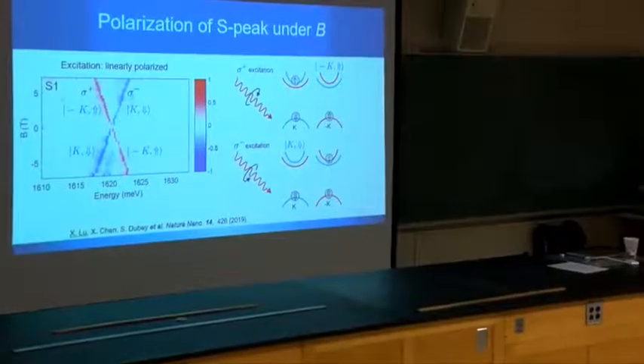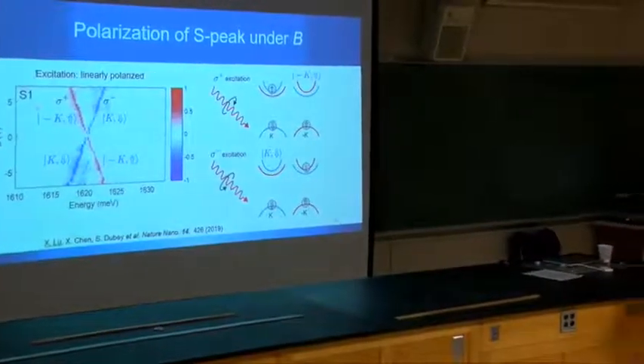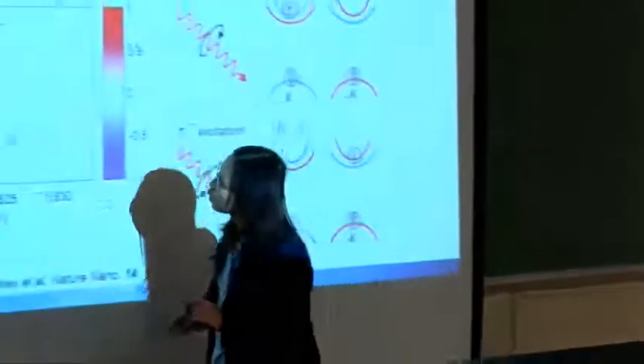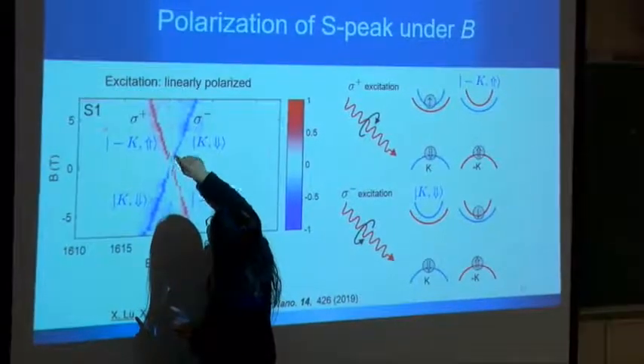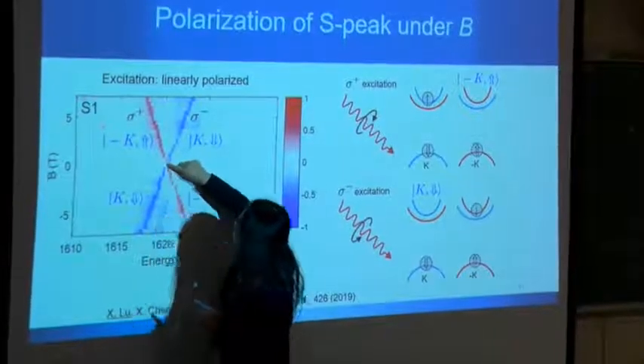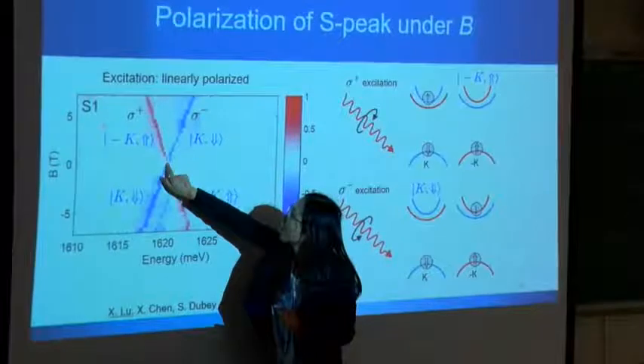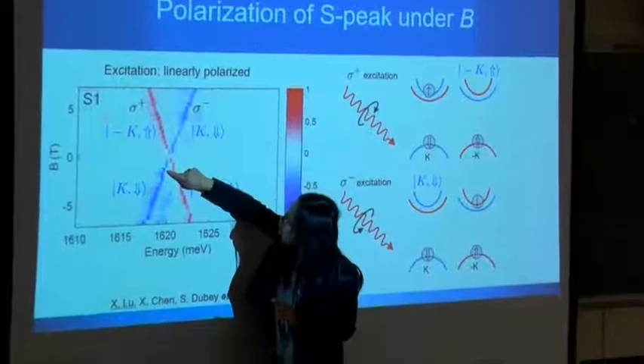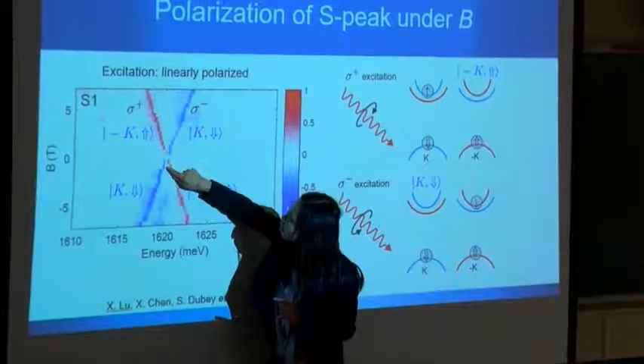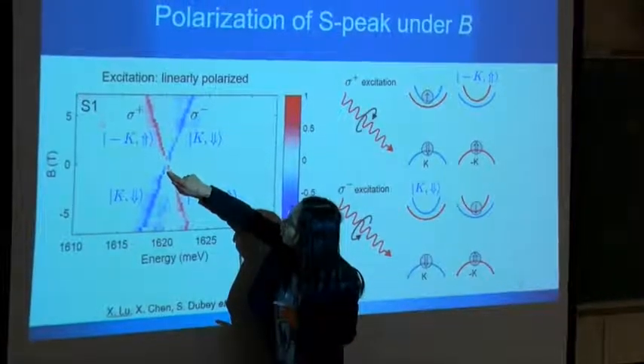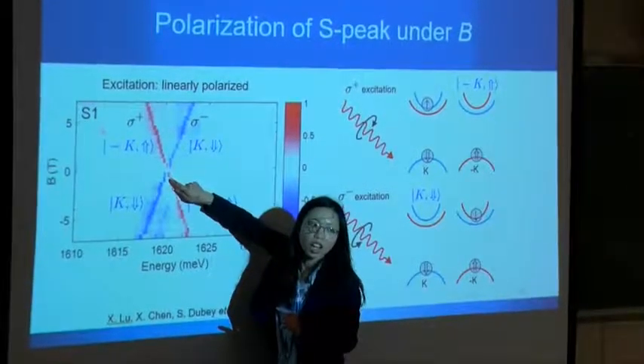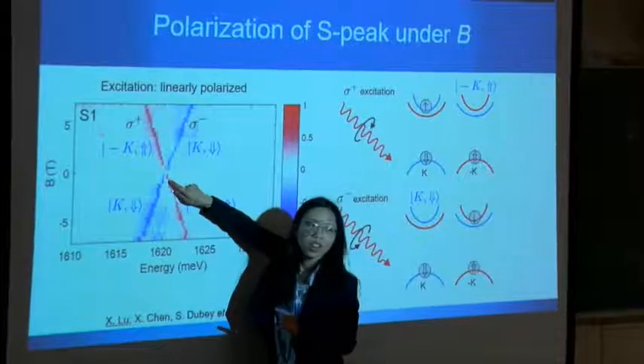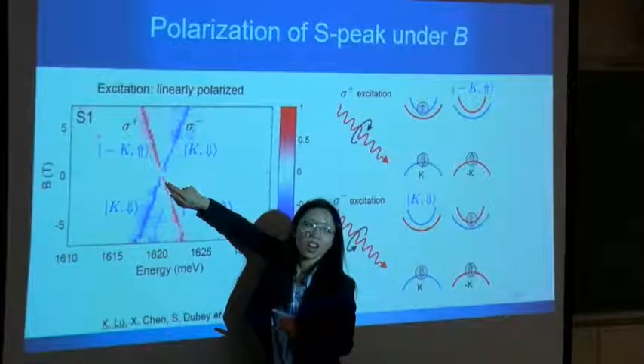I noticed that near the zero magnetic field, that looks like a real splitting in there. These two branches do not cross each other. If you draw a line here, it's actually here. But there's a gap in there, right? That would indicate there's interaction at zero B field. So the ground eigenstate is not just k up or k down, it's the superposition of the two.